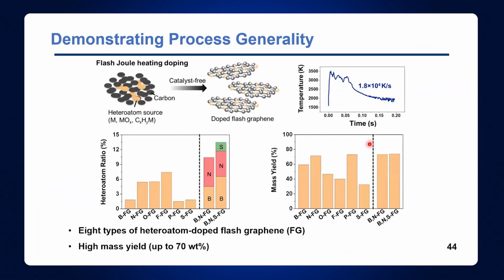And then what we could do is we can put on boron, we can put in nitrogen, oxygen, fluorine, fluorinate the surface, sulfur. We could mix them. We could put boron, nitrogen, or boron, nitrogen, sulfur. So you can put in different elements either on top of this lattice, above and below, or in the plane of the lattice, depending on the atom. Because fluorine can only bind to one thing, it goes above and below the plane. Oxygen can bind to two, so that could be in the plane.